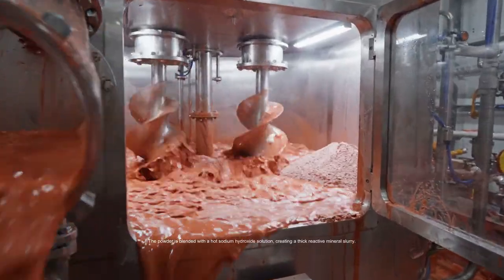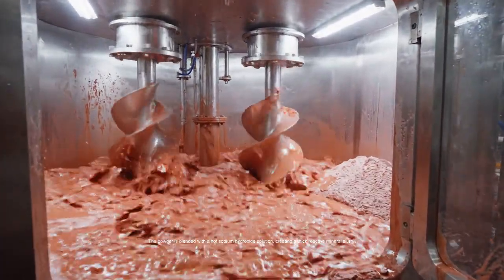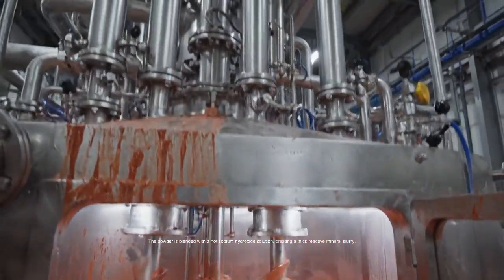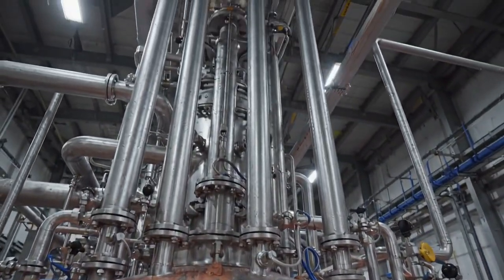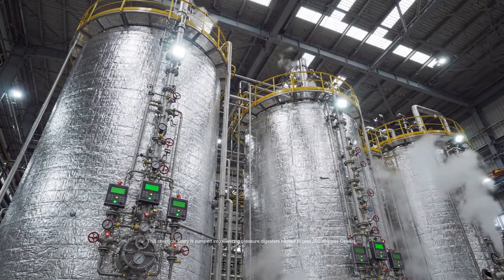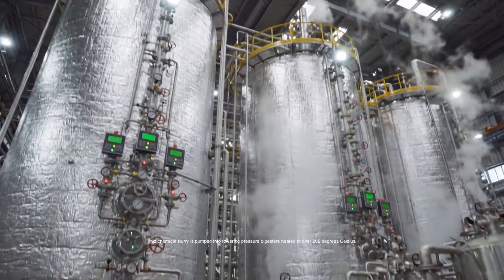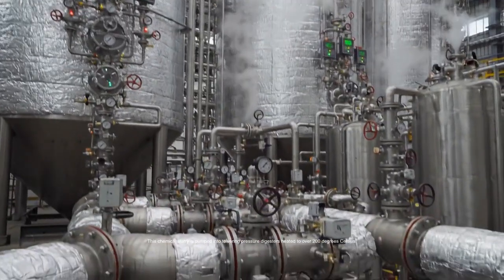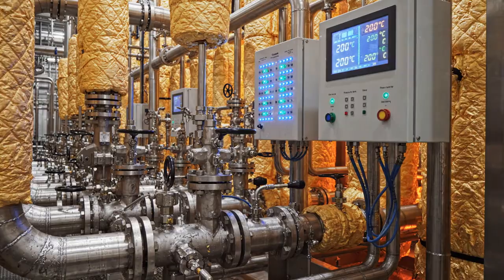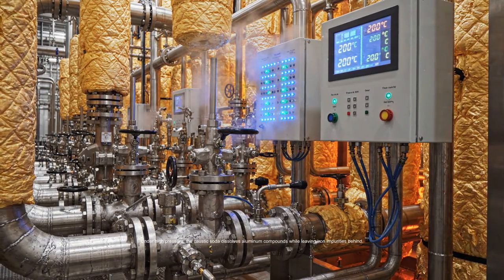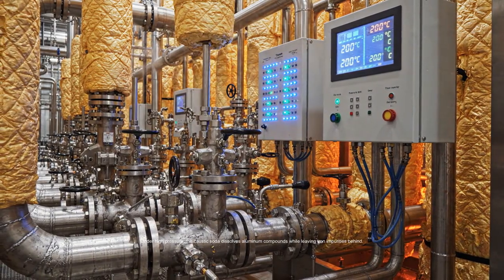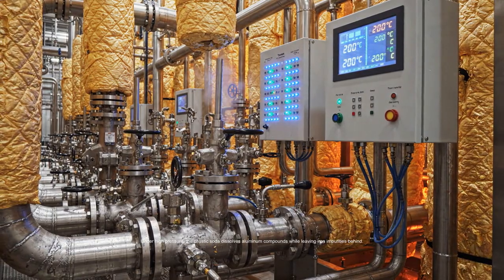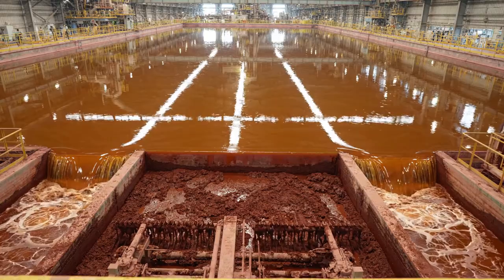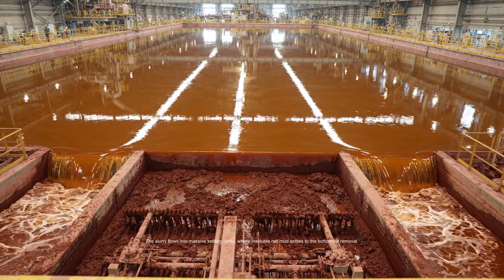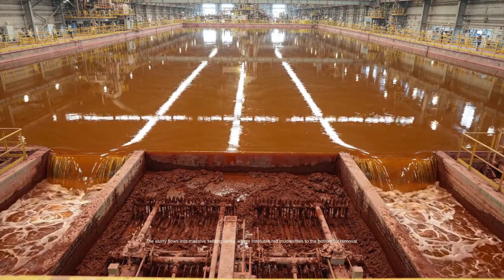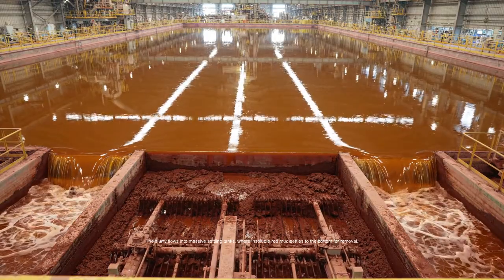The powder is blended with a hot sodium hydroxide solution, creating a thick, reactive mineral slurry. This chemical slurry is pumped into towering pressure digesters, heated to over 200 degrees Celsius. Under high pressure, the caustic soda dissolves aluminum compounds while leaving iron impurities behind. The slurry flows into massive settling tanks, where insoluble red mud settles to the bottom for removal.